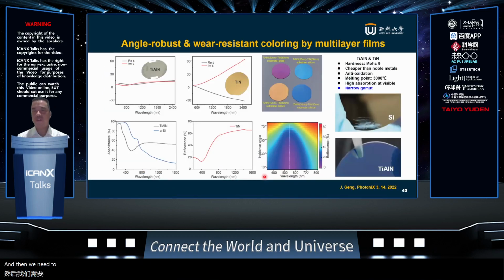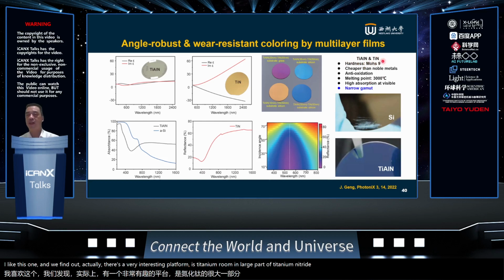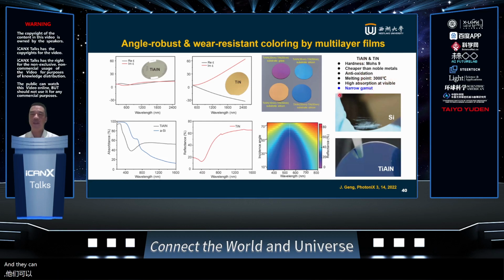And then we need to find a platform to play with. And we need to design very special multi-layer films. Since we want to make a painting out of it, they have to be angle robust. So the colors should be angle independent when you see them from different angles. It also should be wear resistant. I cannot afford beautiful pictures painted at $1,000 or even $10,000 using nanofabrication that you cannot even scratch. And we found a very interesting platform, titanium aluminum nitride or titanium nitride. If we make them multi-layers, they can survive at very high temperatures, and they are very wear resistant.